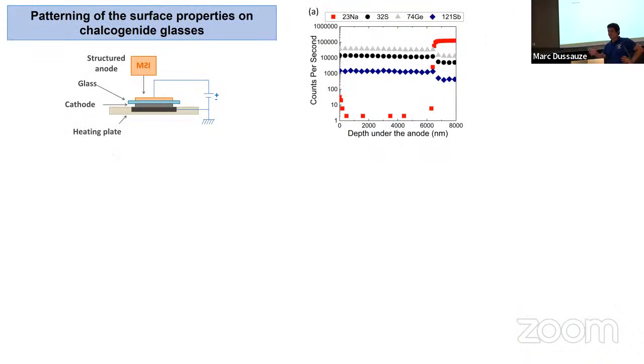We take this glass, we make the poling, and we obtain such a very nice depletion layer, as you can see. The guy who has measured this is here, it's Antoine. It's a 6 micron thick layer of sodium depletion, you see. So you modify the glass for a layer of a few microns, depending on the composition, of course. This is just an example.